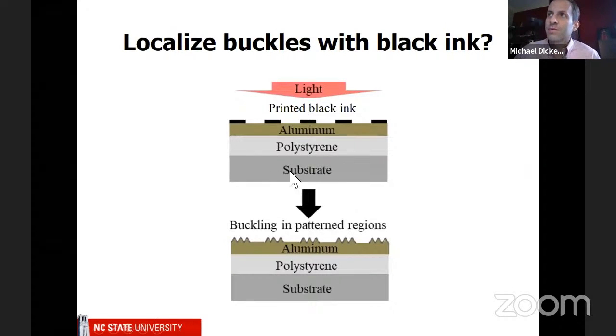or a silicon wafer, which is called substrate here, coat it with polystyrene, which is very easy to do by what's called spin coating. Basically, you put some liquid on there and you spin it, and then it coats it very uniformly. And then we coat it with aluminum. If we put this whole thing in an oven, it would wrinkle. It would form those wrinkles. But instead, we're going to put some black ink on the surface and then shine light. And wherever we shine light, as you know, this black ink can get hot, and this should cause it to form wrinkles. Okay, so let's take a look and see what happened.